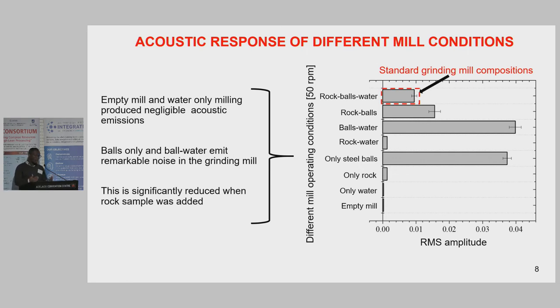Now, for some of our results, which I'm showing for our preliminary test, this result shows different operating conditions of a laboratory AG-SAG mill and their acoustic response or characteristics. We can see that the acoustic response of an empty mill or only water was observed to be comparatively negligible. Excessive noise emission was associated with when we put in only steel balls or steel balls and water inside the mill. And in both scenarios where rock or ore samples were added, we saw that the mill acoustic levels reduced drastically. This shows that different mill operating conditions actually produce different mill acoustic characteristics.